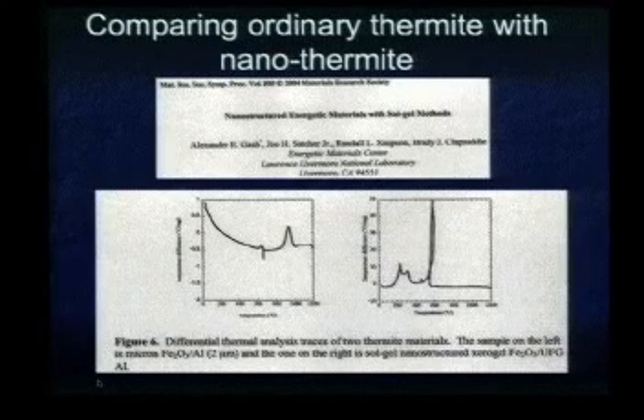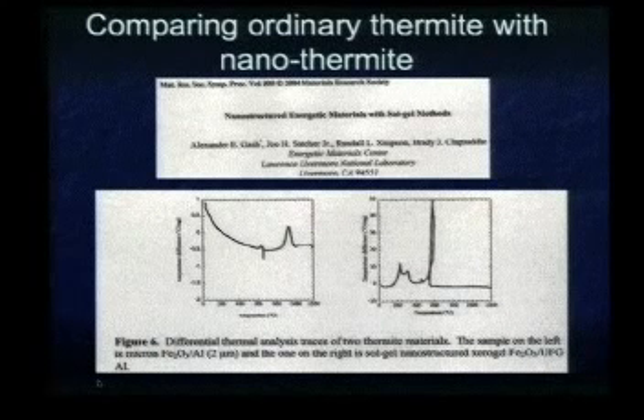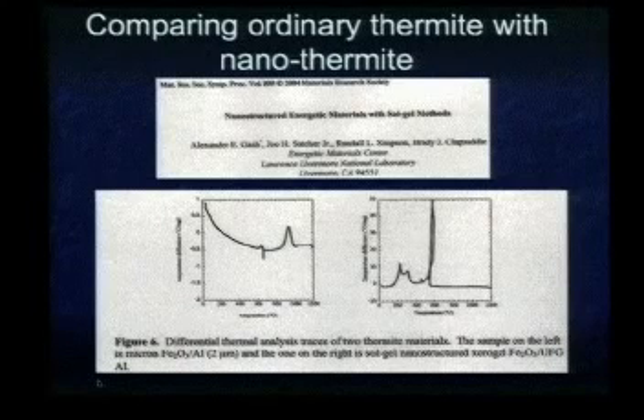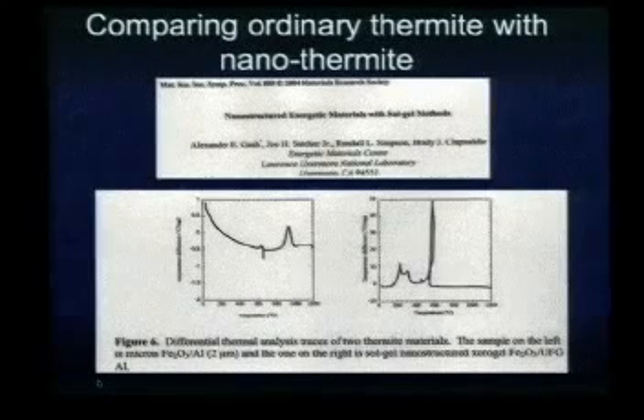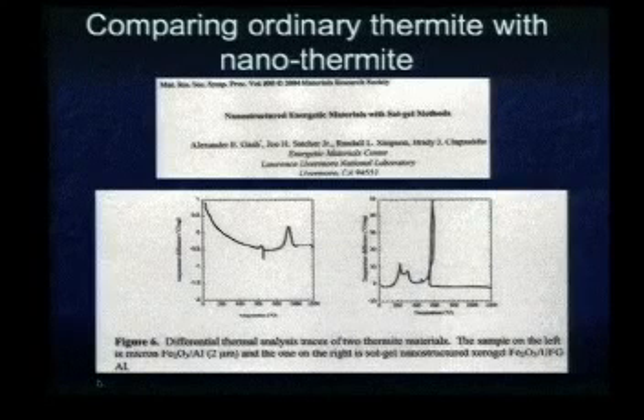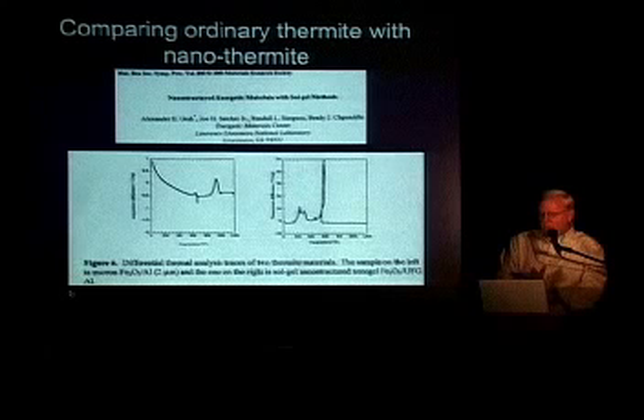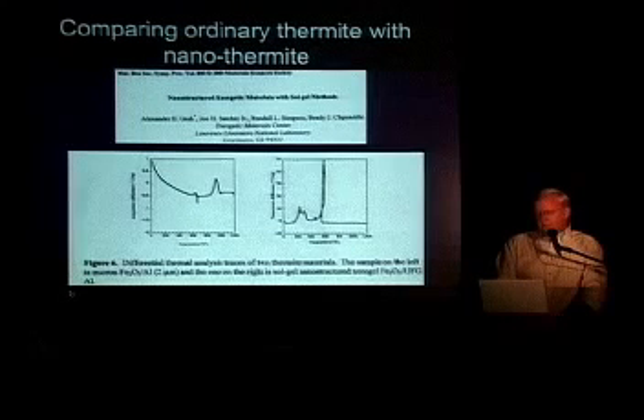If I can help you read the scale, the ordinary thermite goes off at about 900 centigrade, and their nanothermite goes off at just below 600, about 550 in this case, centigrade. Again, the finer the material, the lower the temperature. So that distinguishes nanothermite from ordinary thermite. Notice how much broader the ordinary thermite peak is compared with nanothermite.